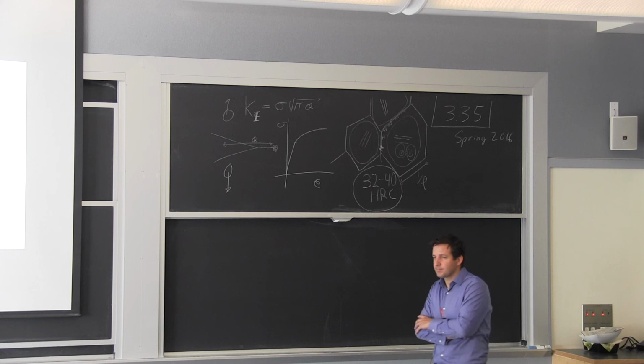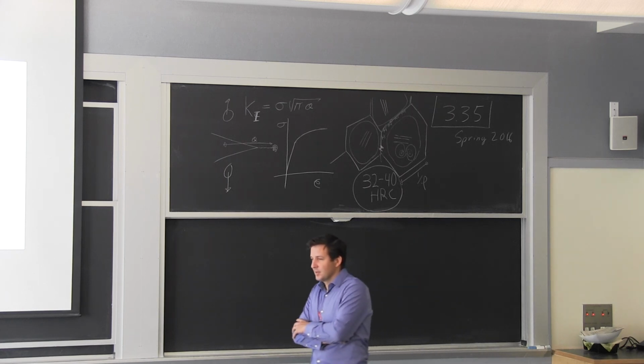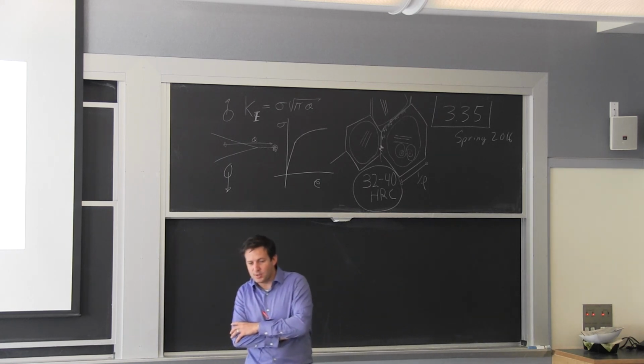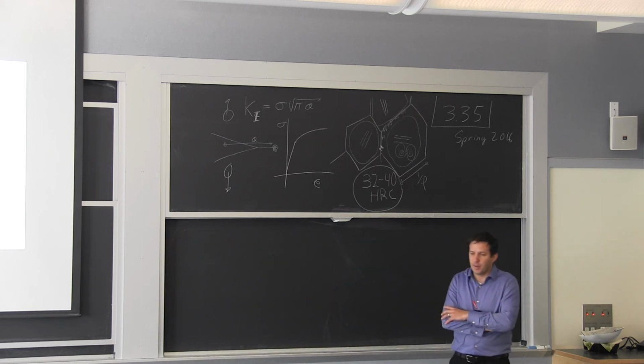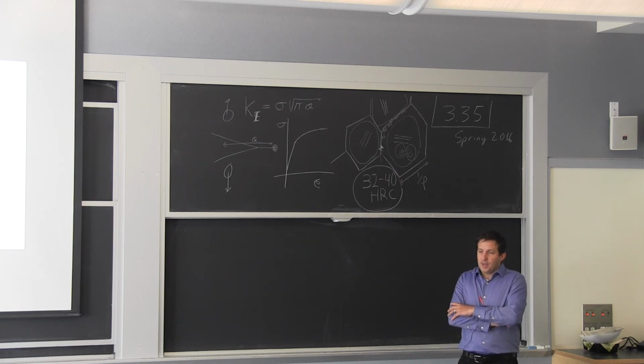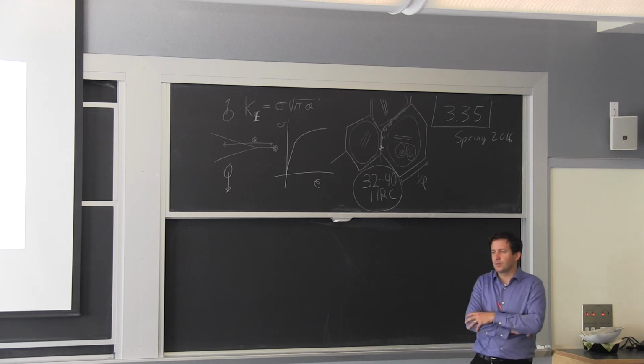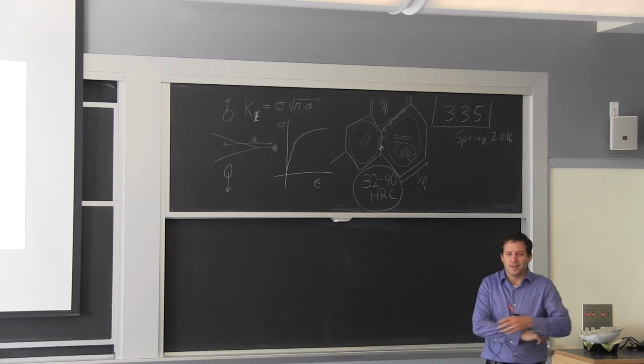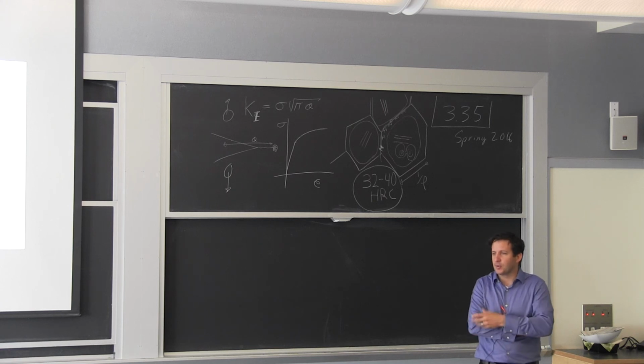Yes? So how do they then have the corrosion protection if they can't use, like... It's a good question. So the main way for high strength material that I'm familiar with is you embed them in grout, and that keeps a passive layer on the surface because you're at a pH in the range of 12 on the surface. Under those conditions, the steel, a little bit like the aluminum at ambient temperature, has a passive state on the surface. And that's the main reason why we do put steel in concrete.